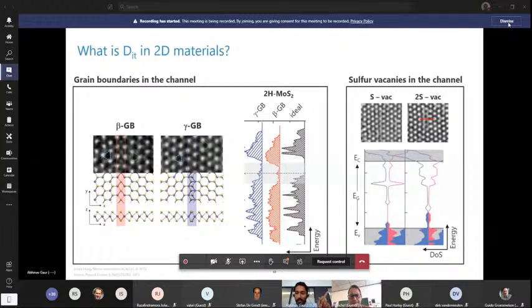So the fact that in this slide, can you see my slide? Yes. So in this slide, the pink and the blue thing that show the sulfur vacancies, the states, show spin up and spin down. So do they show that it could be measured via a spin? It should be, right? Because they can be separated out. I'm a bit surprised as well, because I would expect that a single vacancy, so I don't know if this refers to a line of vacancies here or a single vacancy. I'm not sure about the DFT calculations there, but I would expect that a single vacancy should have some spin polarized effect. So the DOS for the up and the down spins should be different, and you have a spin polarization induced. So it's maybe not a single vacancy which is computed there, but a kind of line of vacancies as they maybe show in the TEM graph there. But something we'll have to check, definitely.